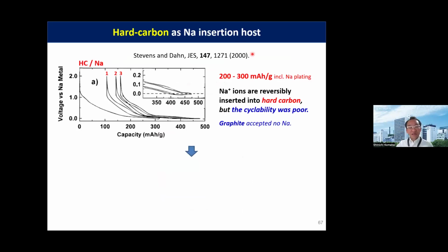So in 2000, Professor Jeff Dahn reported a hard carbon electrode in a sodium cell. The reversible capacity is higher, approaching 300, but the cycle life is very limited. So in this paper, only 3 charge-discharge curves are shown here. And graphite does not accept sodium ion through electrochemical reaction.